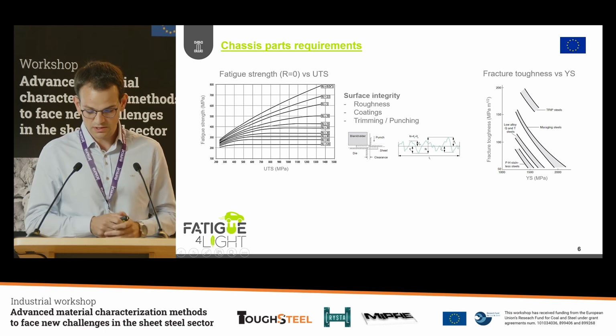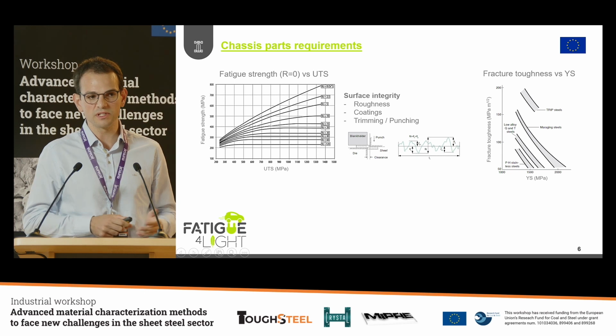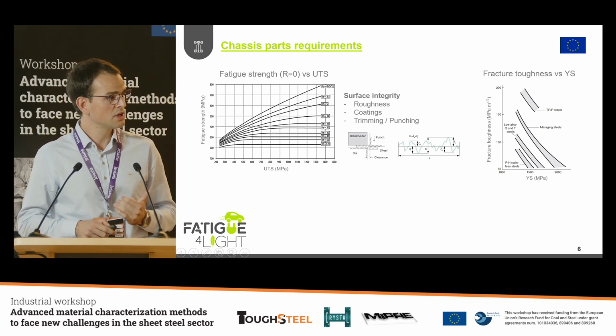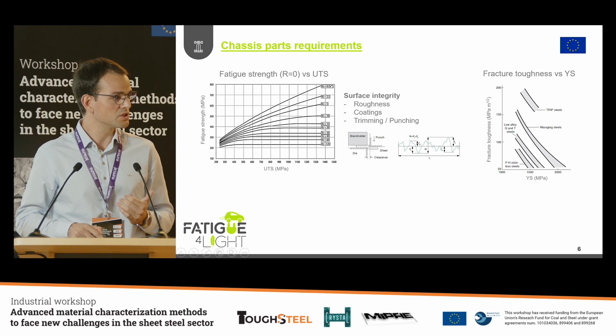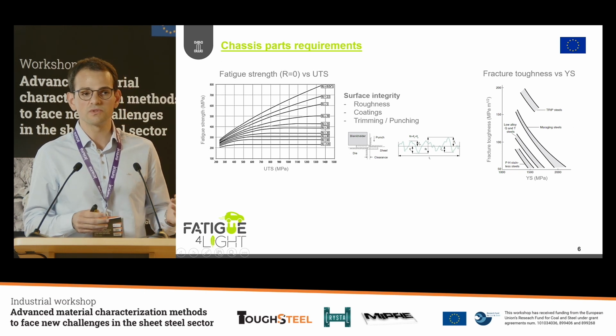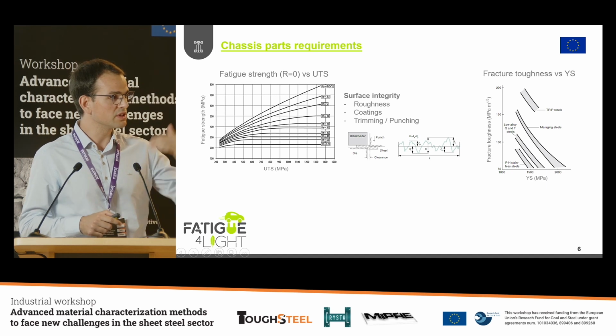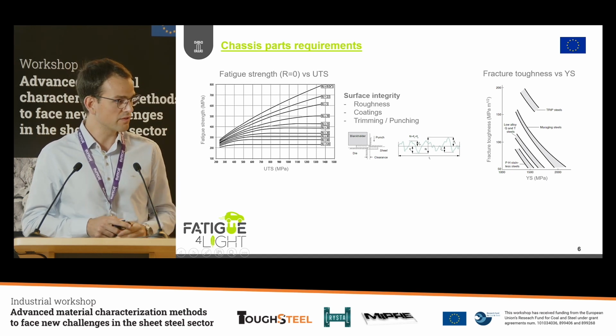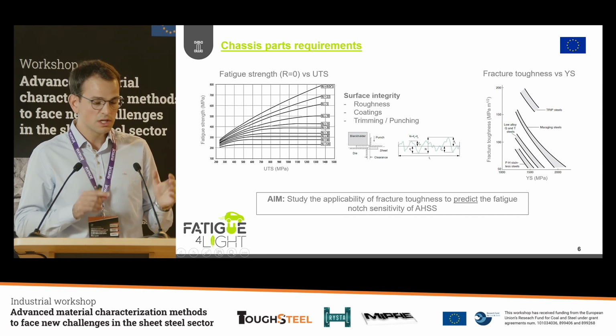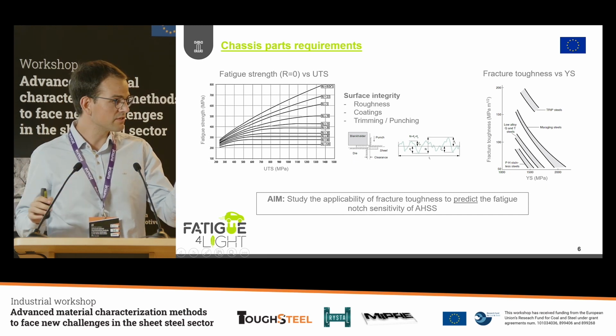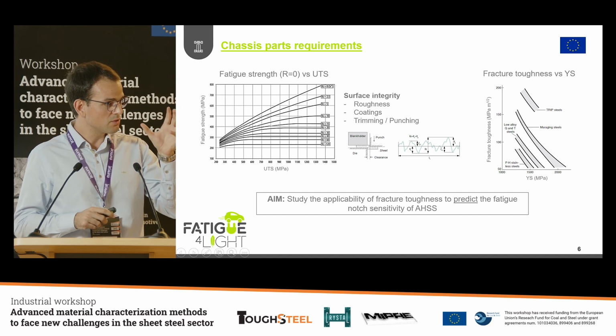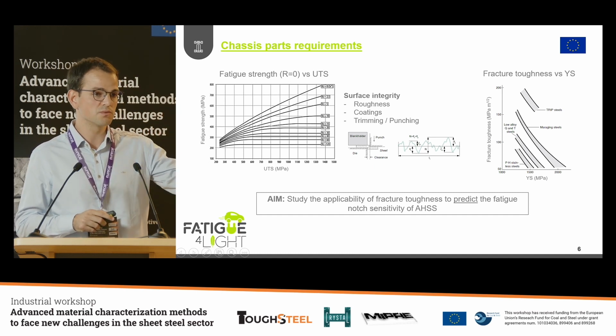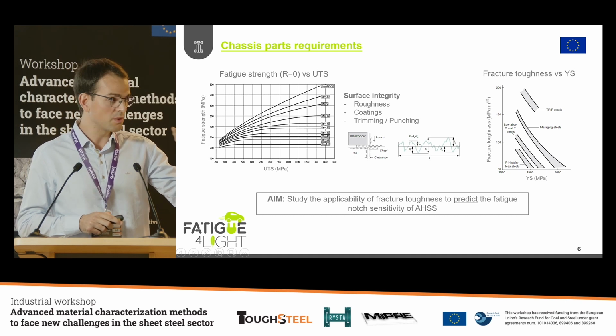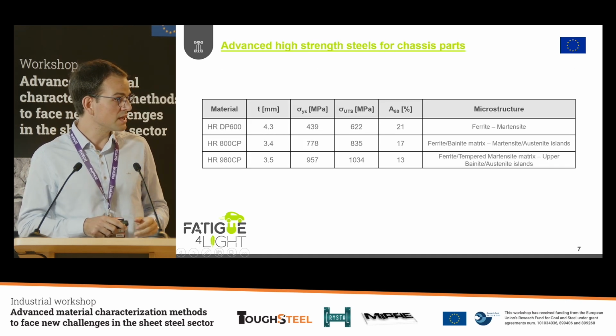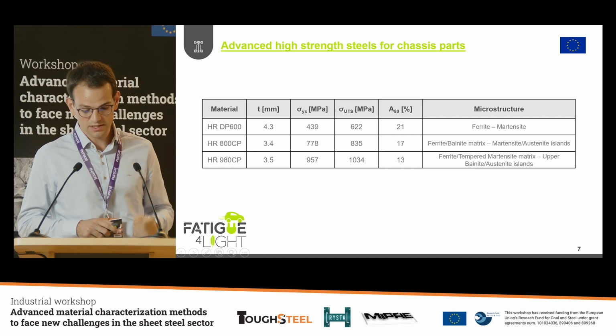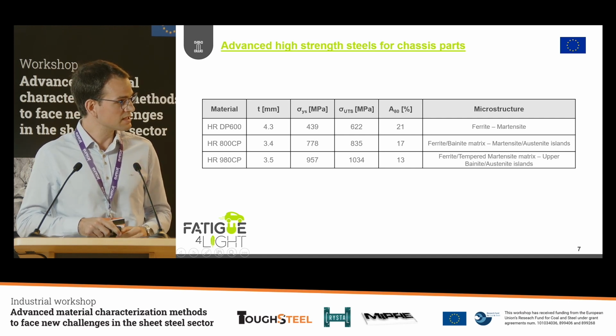in the conventional materials, if we increase the tensile strength of the material, the fracture toughness is reduced, but not for all the materials. So, for instance, for a given yield strength, we can move to another material with another microstructure to maintain this fracture toughness or even improve it. So the aim is to use these two different properties, fracture toughness and fatigue, and see how we can use mainly the fracture toughness properties to assess which will be the fatigue resistance when we have a defect in the component.